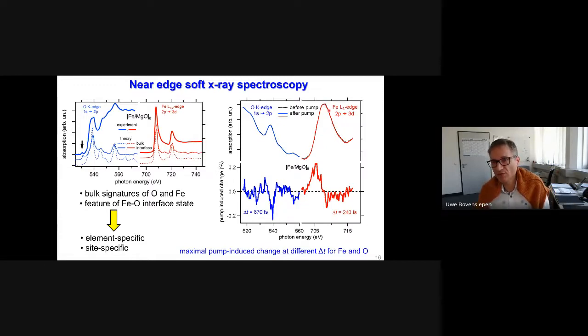So you see here before, this is the black dotted line, and the red and the blue line, this is after pumping. So you can see some small differences, and we can plot the pump-induced change here by just calculating this difference down here. And you see we have to struggle to accumulate data, but there are clear signatures that we can find within a given beam time.